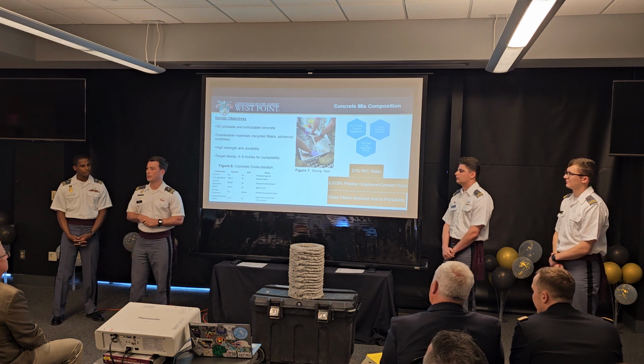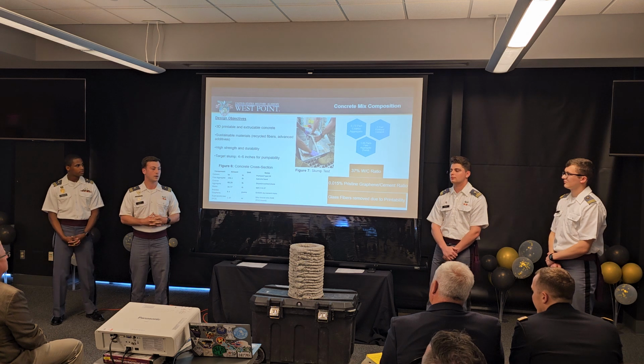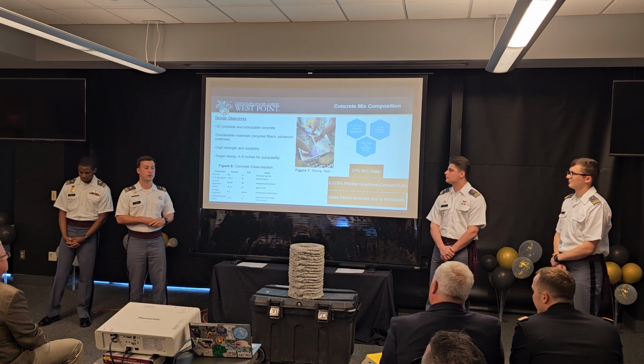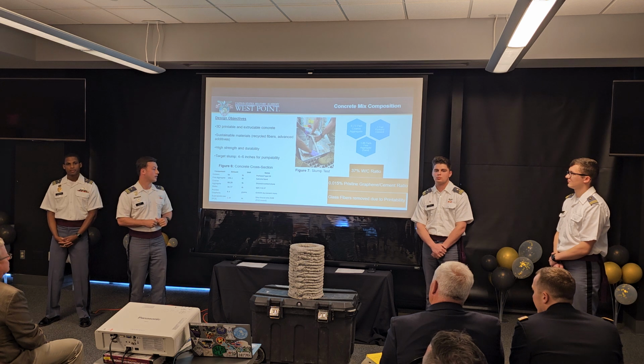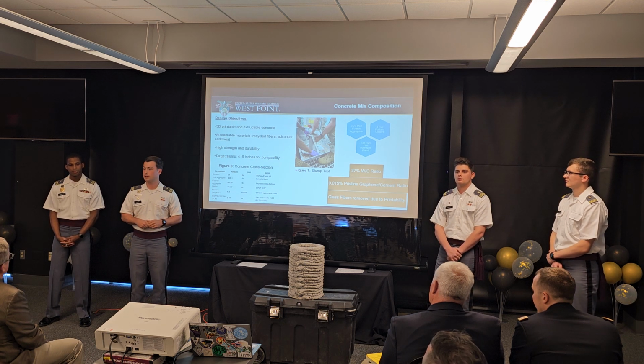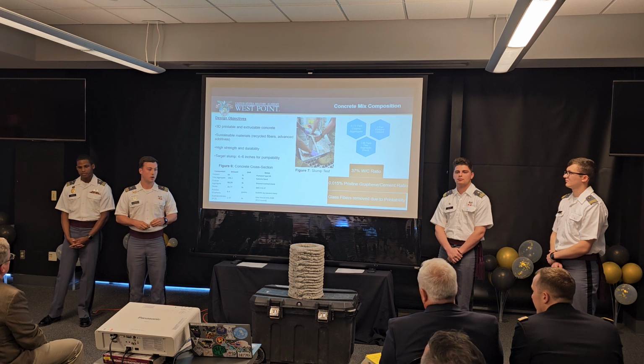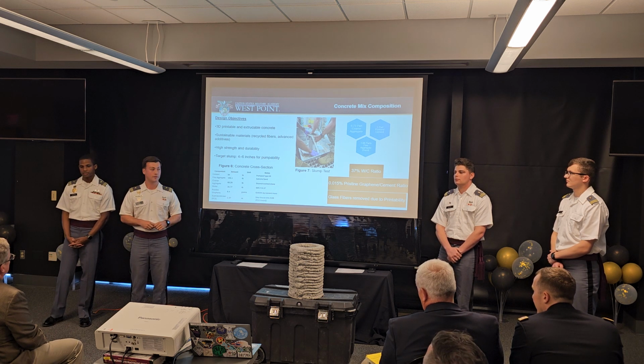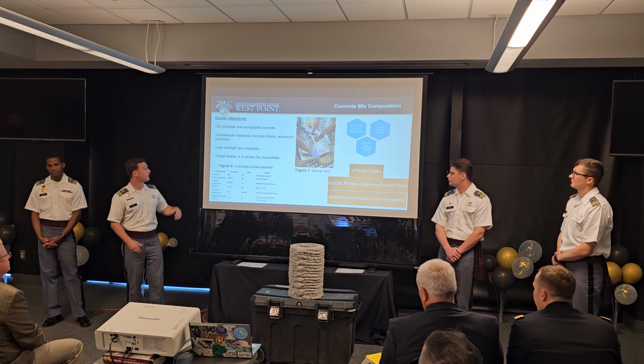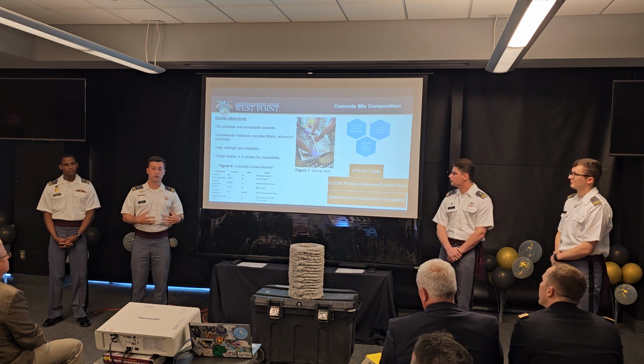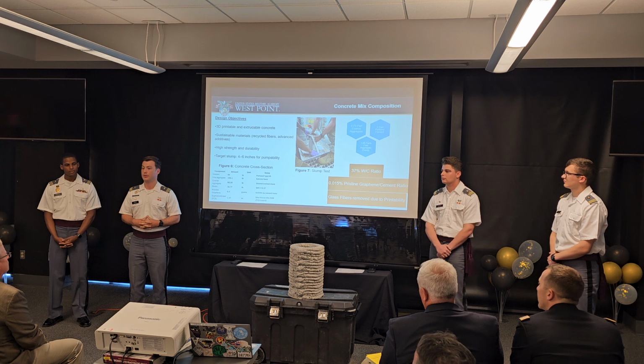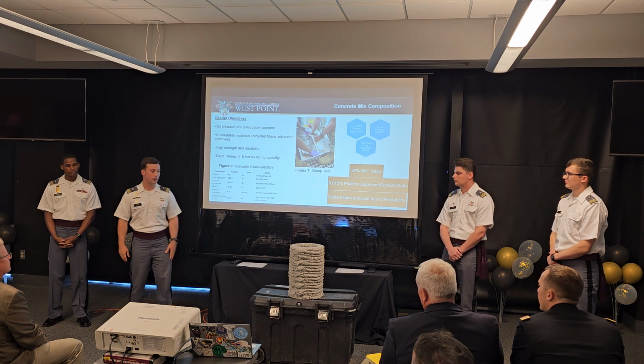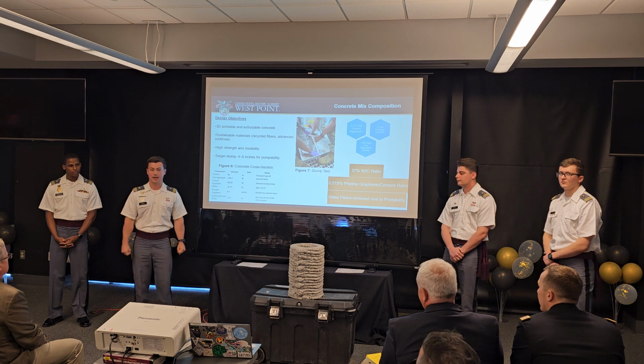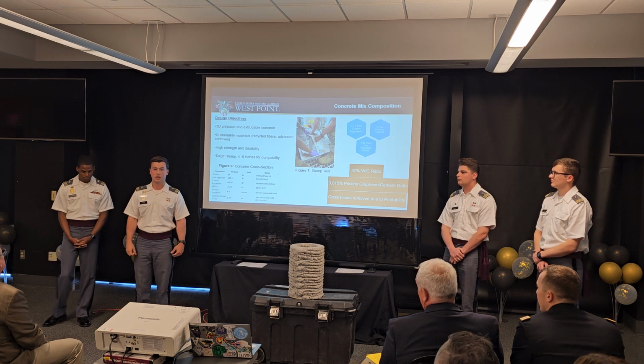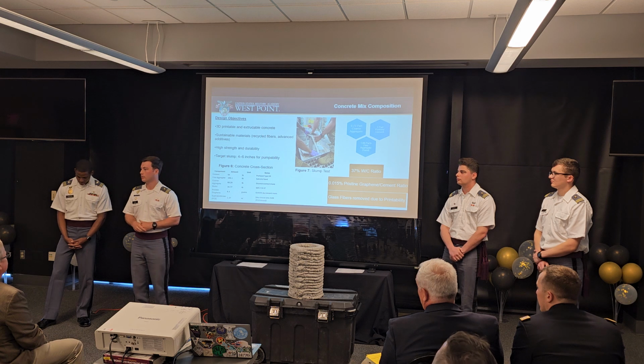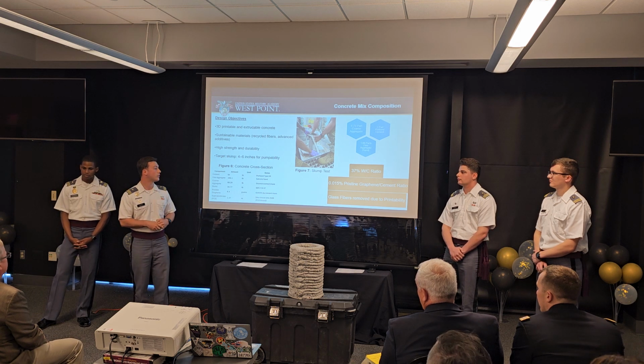And as Leslie kind of mentioned, we wanted to carefully manage our quantity of pristine graphene. As we said, it aids strength, but we wanted to do so at an efficient level. We decided, and we'll show later, that at a 0.015% compared to our relative weight cement, that was our perfect and optimized concentration. And finally, we'll talk about this additionally, but we were forced to remove the recycled glass fibers for the 3D printing component. So this prototype right here does have pristine graphene in it. It does not have glass fibers because of their reduction in flow. And that's something that we anticipate we can move forward with for further 3D printing.